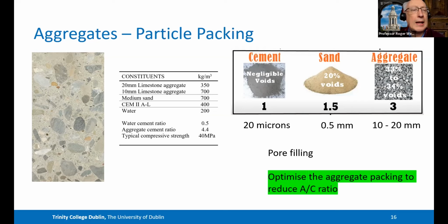And then if you look at the diagram on the right-hand side, you can see that the voids is typically about 30% in aggregate. So the voids that exist between the stone have to be filled by the sand, which is typically much smaller in size. Then the cement glues it all together, but it also has to fill up all the voids. So if you don't design the mixture of your stone, both in terms of its size and the quantity, grade it very well, you're going to have a lot more cement that's necessary.